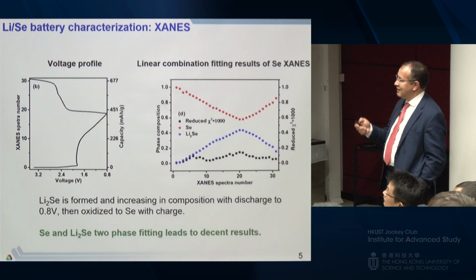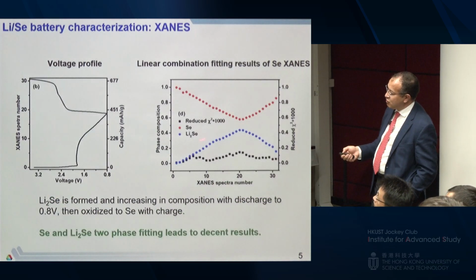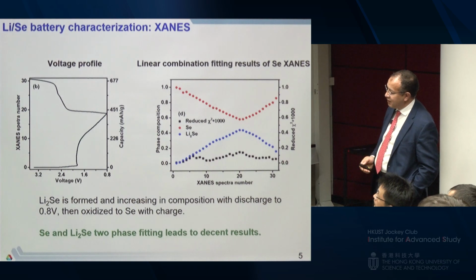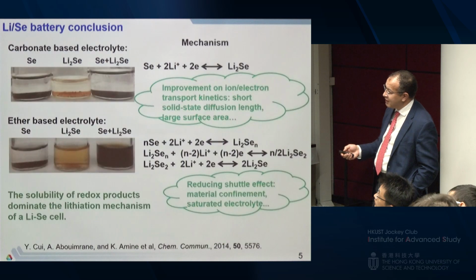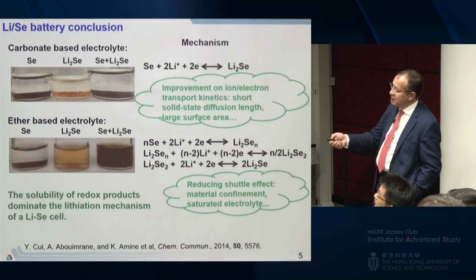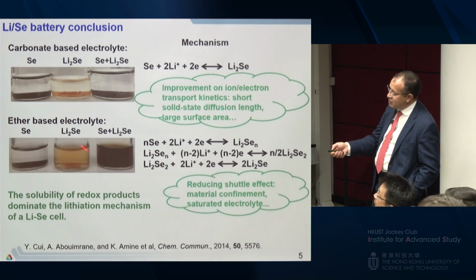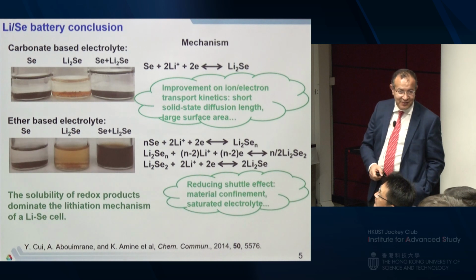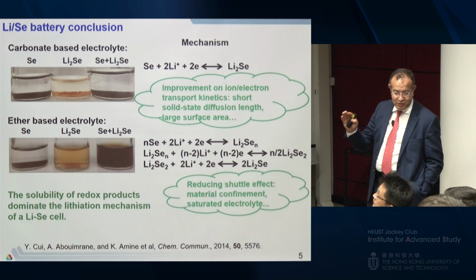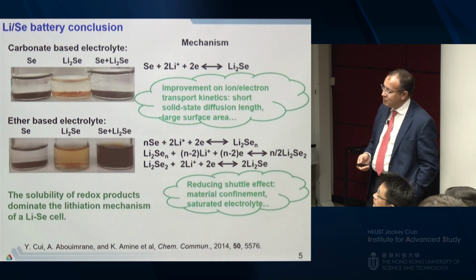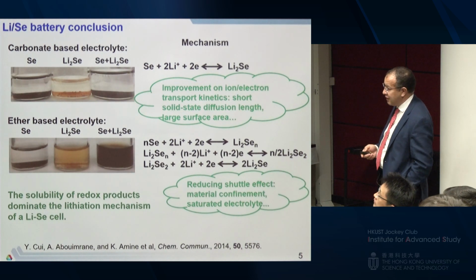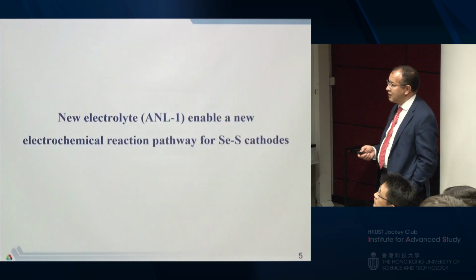And you see the fitting is just two phases in this case with the carbonate, but the dissolution does not exist here, and we actually did a dissolution experiment. If you take a carbonate and use polysulfide, it doesn't dissolve, you can see. When you use the ether-based electrolyte, it dissolves. So we confirm that with carbonate there is no dissolution, but with the ether-based there is dissolution. So now what we need to do is design a new electrolyte that works, and we did.